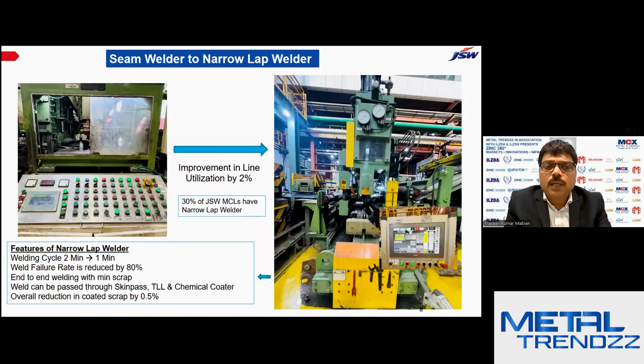Here are a few photographs. The earlier conventional overlap welders were replaced with the narrow lap welder, with a very reduced weld cycle time. This gives us reduced scrap generation because we can always pass these welds through the skin pass and tension levelers as well as the coater. 30% of JSW metal coating lines have a narrow lap welder. This has improved utilization of the metal coating lines by 2%.